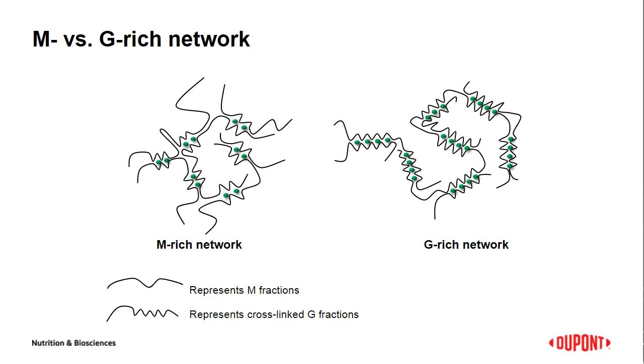As described before, M blocks in the alginate form random coil structures in solution. These form mostly entanglements and enhance the viscosity. But these M-rich structures are not able to coordinate calcium ions very efficiently and only form weak gels. Therefore, the source of the brown seaweed is of high importance. Laminaria hyperborea is a source which offers alginate with high portions of G blocks, forming rigid gels as soon as the calcium ion concentration is increased.